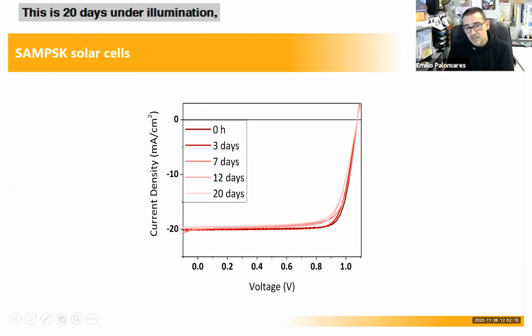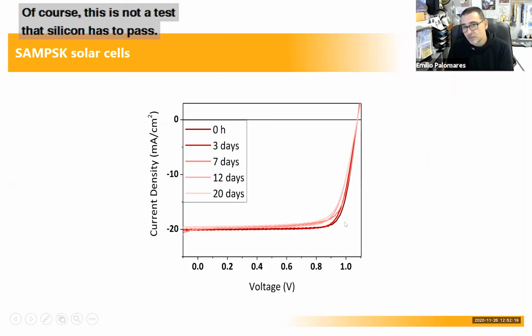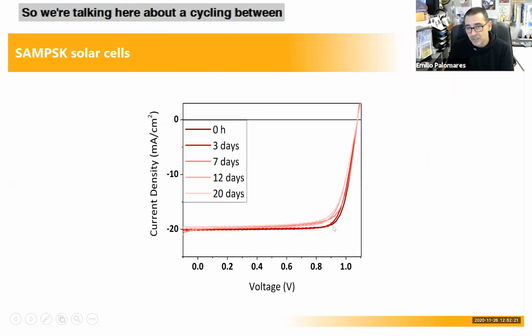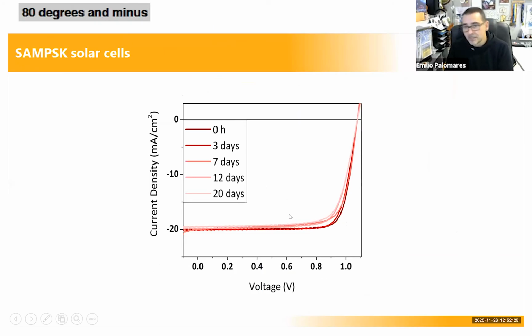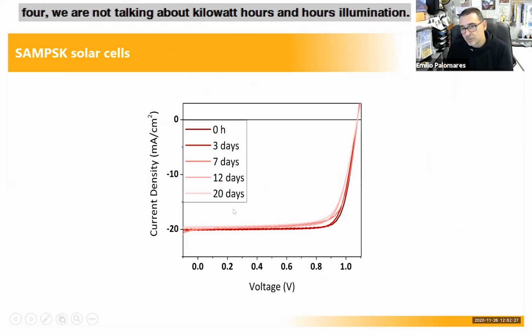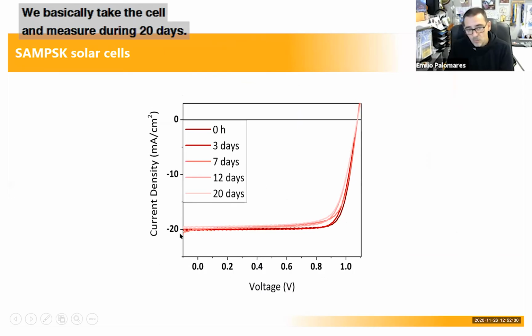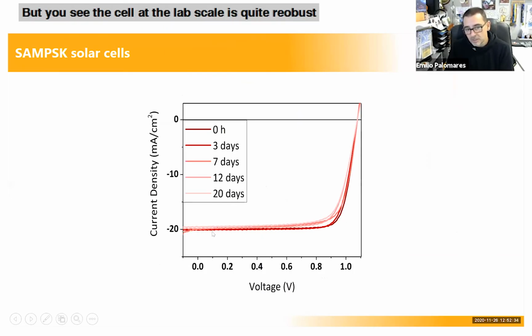This is 20 days under illumination, almost no degradation at all. Of course, this is not a test that silicon has to pass. So we're talking here about cycling between 80 degrees and minus 40. We are not talking here about 1,000 hours illumination. We don't do this at the lab. We basically take the cell and measure during 20 days. But, you know, you see the cell at the lab scale is quite robust.